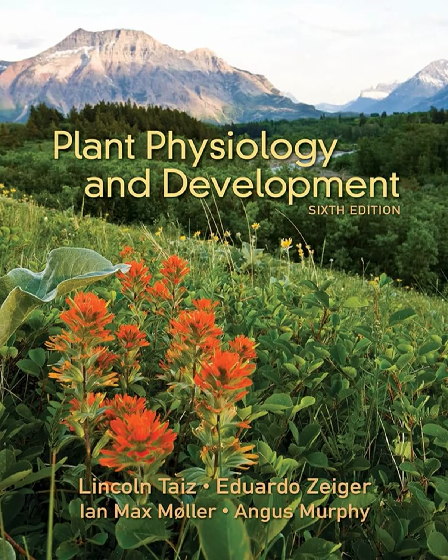Randomly linked? Pretty much. Unlike the precise structures of cellulose or proteins, lignin doesn't have a defined repeating sequence. It fills the spaces between the cellulose and hemicellulose, kind of like embedding the polysaccharide framework in a hard plastic-like resin. And that makes it strong and waterproof. Exactly. Lignification drastically increases the wall's compressive strength and stiffness. It also makes the wall hydrophobic.